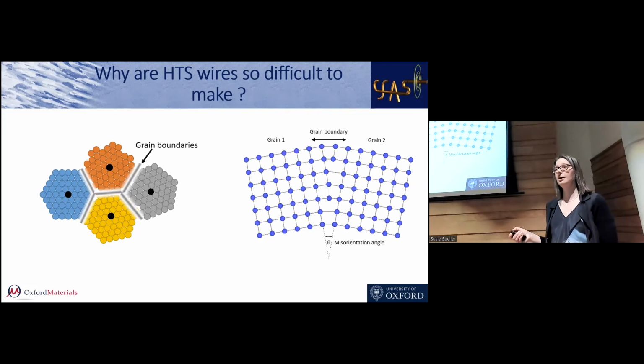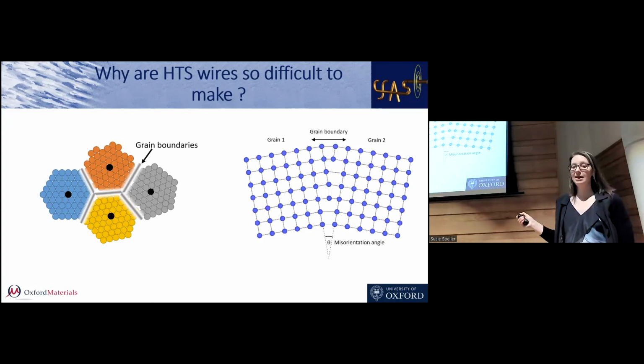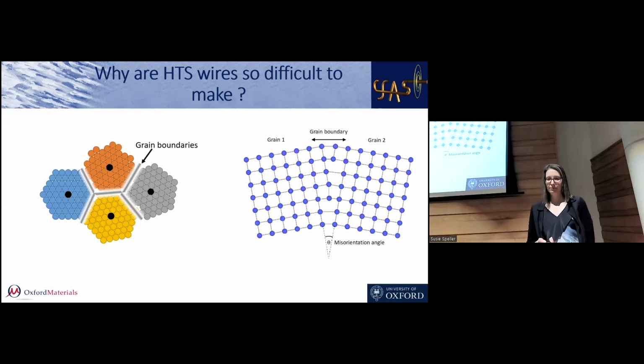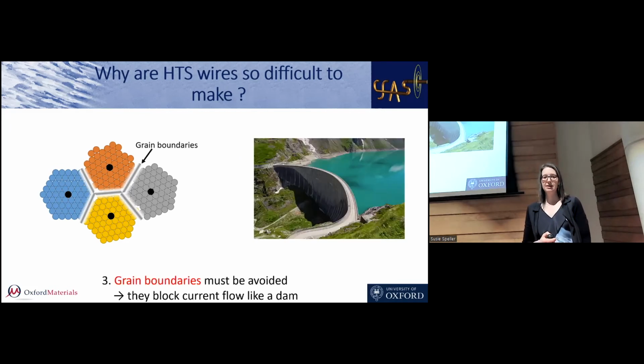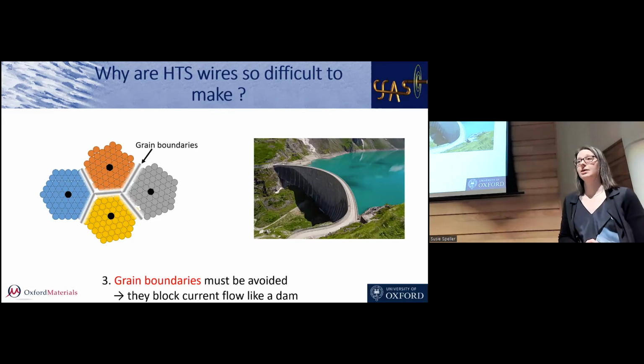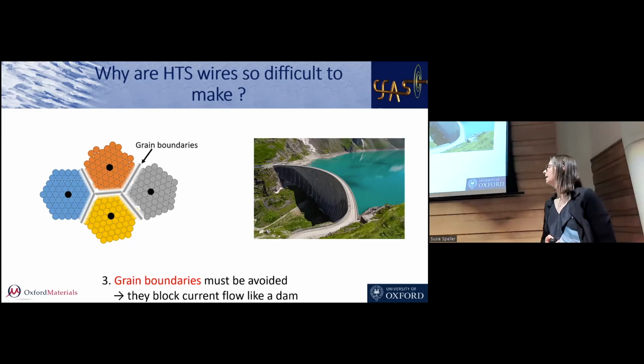So they've got a misalignment at the boundary. We call them grain boundaries. And here you can see one just shown schematically. They've got a particular angle misorientation, so they're not lined up properly. And the problem with high temperature superconductors like these is that those grain boundaries are enough to block the current flow. So they behave like a dam. They stop the current flowing through the material. So we can't have any of those grain boundaries at all. Most materials are full of them, and we have to work quite hard to get rid of them.